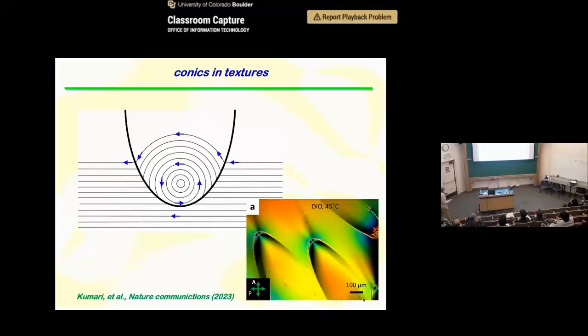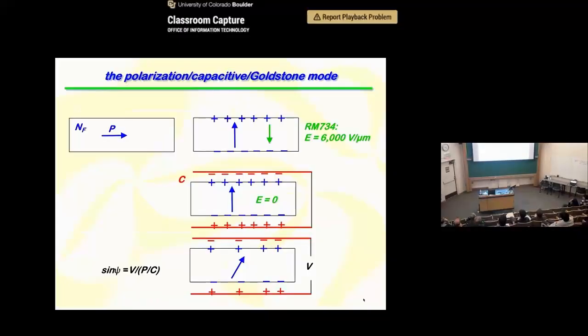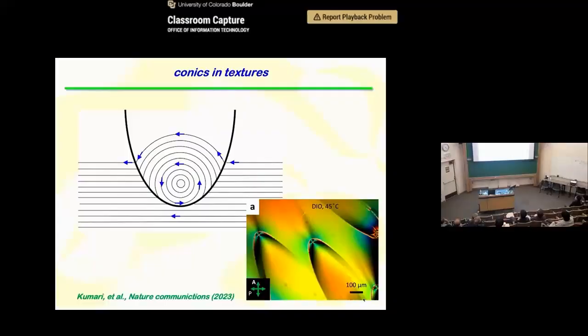Okay, so another way of eliminating, so this is sort of tilting the polarization out of the plane. Now, if you have a slab, then there's the in-plane texture, and that's sort of free to do whatever it pleases. So you can get two-dimensional patterns where there's no space charge. For example, here we have a bend region and a planar region. So there's a boundary here. The boundary line is a focal conic,